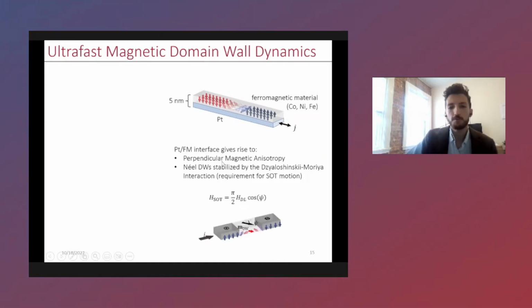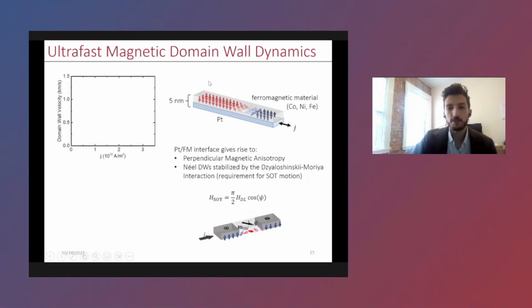And this is important because these types of spin-orbit torques, these traditional spin-orbit torques for materials like platinum, really only act on domain walls with some Néel character. So the strength of the torque is a function of the domain wall angle. And so this device works pretty well. These material systems work okay. So here I'm plotting the domain wall velocity as a function of current density we're applying through the spin-orbit torque creating layer. What you'll find is that you can achieve domain wall velocities that are on order of a few hundred meters per second, which seems reasonably fast.